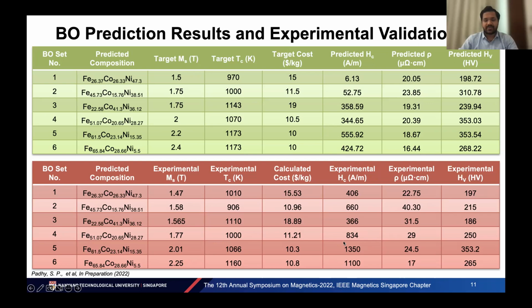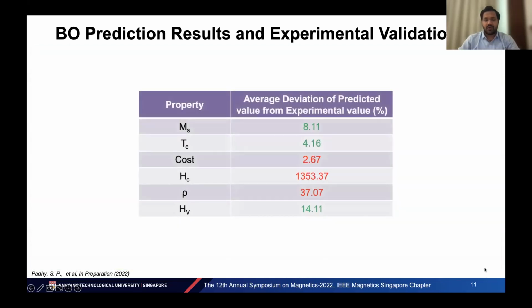In the second table, this is the experimental validation of the compositions predicted by the Bayesian optimization. If I can get your attention to the last two compositions, we can see that the prediction of the Bayesian optimization was very close to the experimental values. Also, the combination of high TC, low cost, and moreover, high hardness was observed. Overall, this is the average deviation of the predicted property values from the experimental values. We can see that MS, TC, cost and HV were the most stellar performance predictions by the Bayesian optimization.